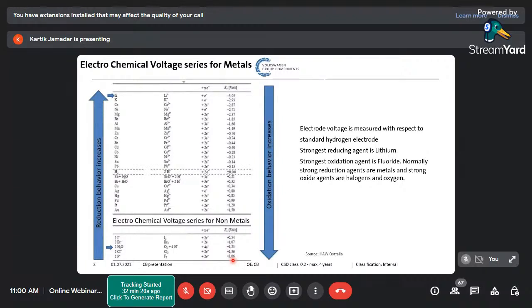But unfortunately, fluorine and lithium react explosively, and it is difficult to break them apart again. When you want to make a primary battery, that is a one-way battery, it is not a problem. One can maybe use it. But for a secondary battery, we want the lithium to come back to its original position. At that time, the fluoride will not release that lithium. You would have to give a very high energy to release the lithium from the fluoride. So fluorine was out.